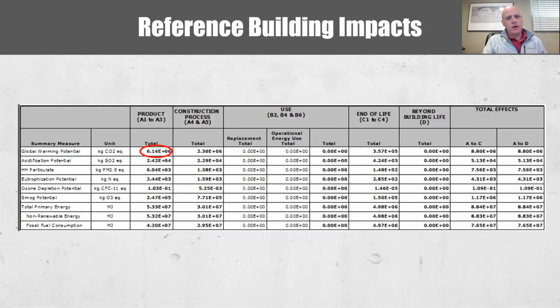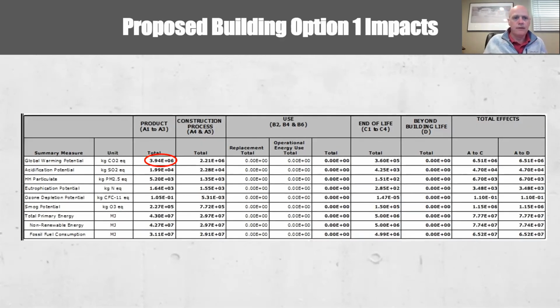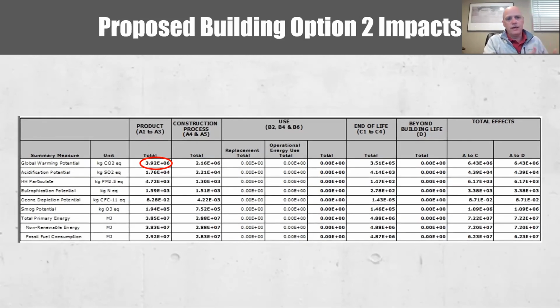So you run the program once and it gives you global warming potential. It also gives you all the other impacts that, if you're designing a LEED building, you'll need to know to meet the whole building LCA credit. But in this case, we're just focused on global warming potential. And you can see, in this case, 6.14 times 10 to the 6 kilograms of CO2 equivalents for, again, all the concrete on the project. Run it again for the low impact slag cement mixes. And you can see it's significantly reduced, 3.94 times 10 to the 6. And then once again for the slag and fly ash combination, here it's 3.92 times 10 to the 6, very similar.